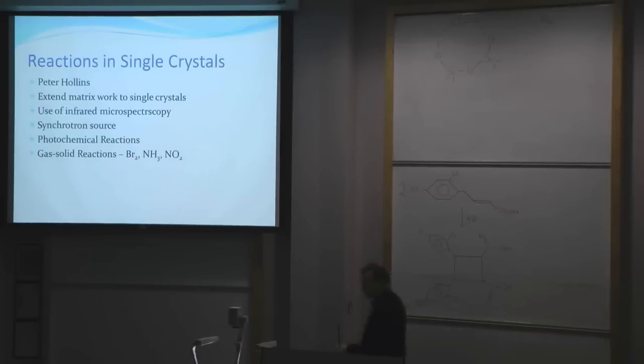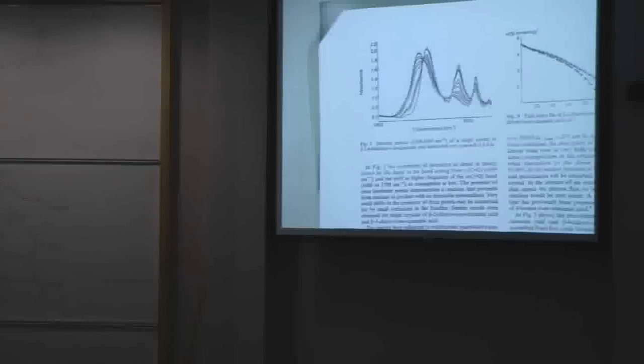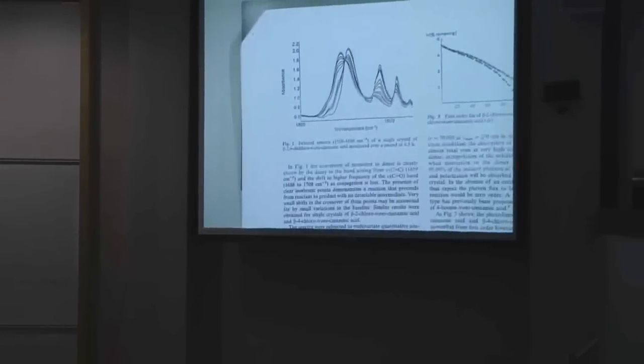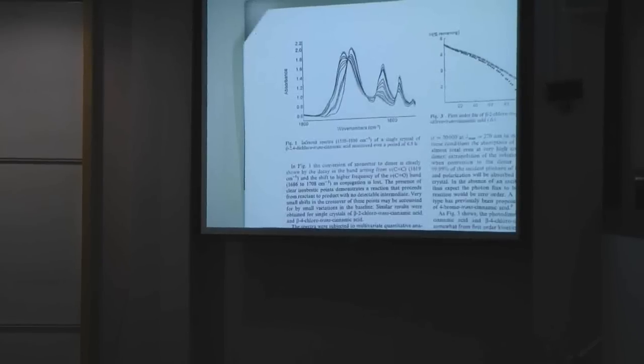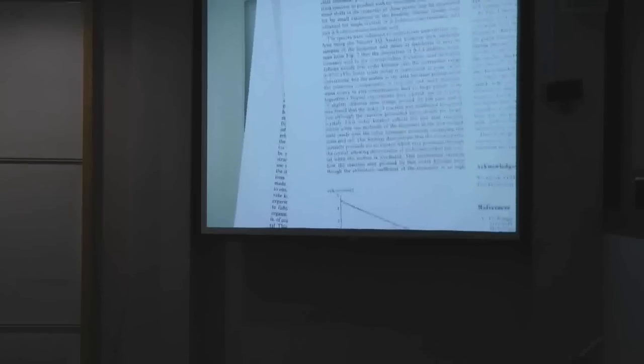So we did some experiments. Actually, I think we did some quite nice things. You can monitor the reaction kinetically, and you could get lots and lots of these scans, but you can see a peak here of the monomer disappearing with time, and a peak of the dimer increasing with time, and you can monitor that over quite a nice time period. This is for the 2,4-dichloro derivative that we've put up here. That gave particularly nice results, and you can get nice first order kinetic plots from it.